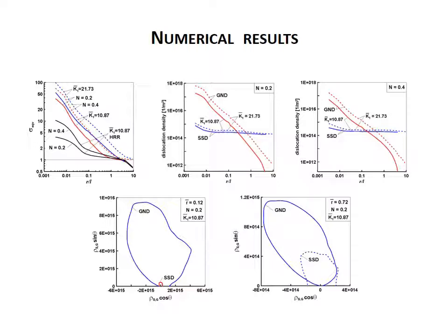As a consequence of the strain gradient contribution, finite element analysis shows a significant increase in the magnitude and extent of the difference between the crack-tip stress fields of conventional gradient plasticity and higher-order theories when the material length parameter is considered. The stress level in this field is three or more times higher than that in the higher-order field within a zone on the order of microns around the crack-tip.